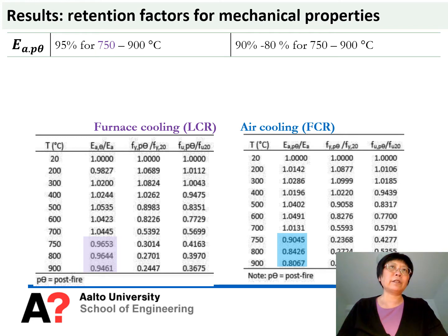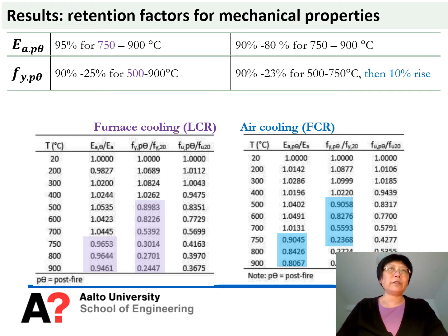So the retention factor is about 95% for furnace cooling and about 90 to 80% for air cooling. And the retention factor for yield strength reduces at about 500 degrees, and varied from 90% to 25% when the cooling temperature is between 500 and 900. And the ultimate tensile stress reduces at about 400 degrees, when the cooling temperature is about 400 degrees.